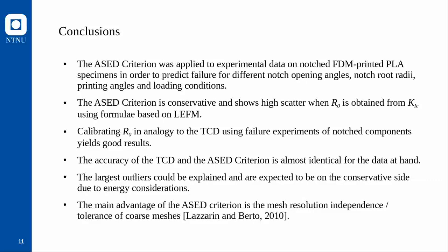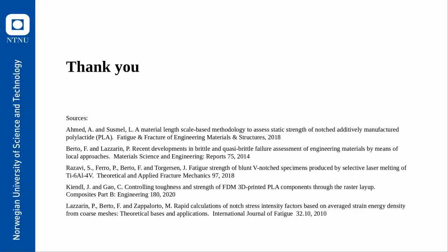Almost, but not entirely: there are some outliers on the conservative side, which we could explain, and based on energy considerations we expect them always to remain conservative — which is favorable. One may ask: if TCD and ASED have the same accuracy, why use ASED? The main advantage of the ASED criterion is its independence from mesh resolution — its relatively high tolerance for coarse meshes — as documented in a number of sources. This is the main motivation. This concludes our investigations. Thank you very much for your attention.